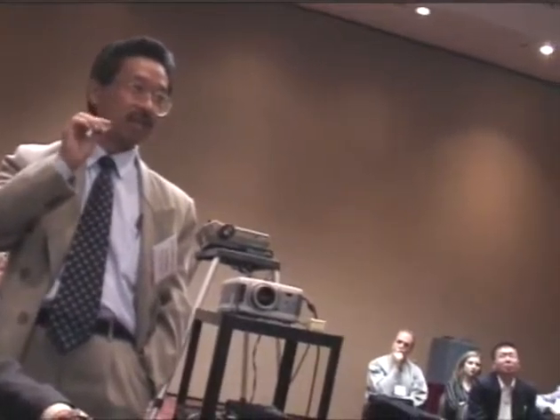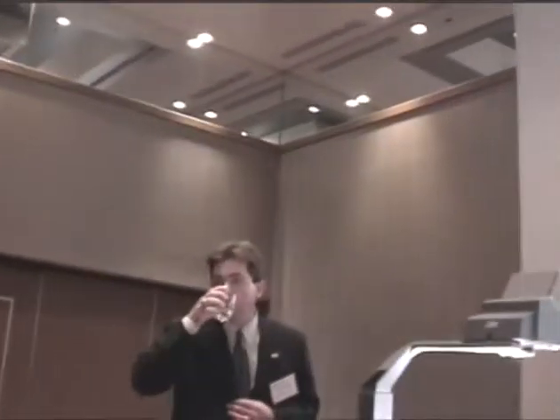You show the ratio of oxygen to the cerium and zirconium is larger than 2, but you still see some oxygen vacancies formed. Generally, if the ratio is larger than 2, this is an oxygen-rich condition. Maybe if it's less than 2, it's oxygen deficiency, or some oxygen vacancies can be formed. But you show that it's larger than 2, and still see some oxygen vacancies formed.